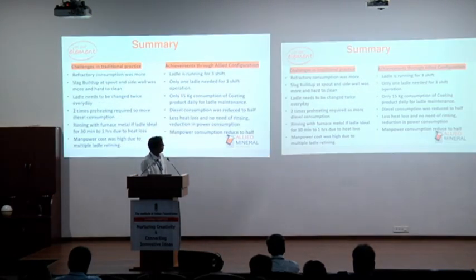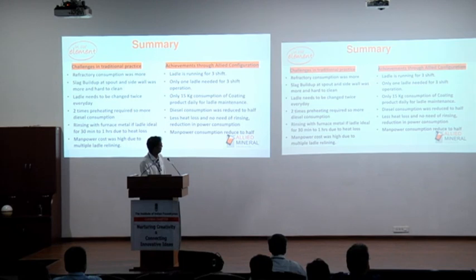So, in summary of that particular case study, the refractory consumption was more in the traditional practice. There was a lot of slag buildup in the spout and side walls, and it was very hard to clean. The ladle needs to be changed twice every day. Two times heating is required, and more diesel consumption was there. So, rinsing with the furnace metal if the ladle is idle for more than 30 minutes to 1 hour due to more heat loss. Manpower was high due to multiple ladle relining.